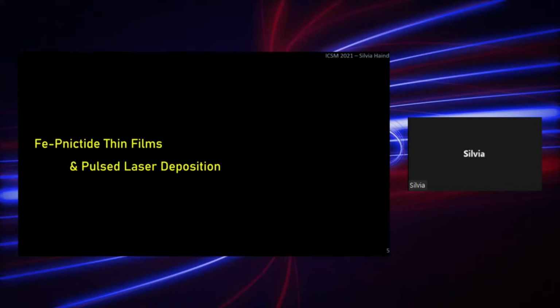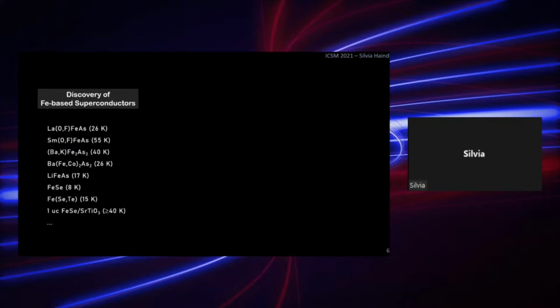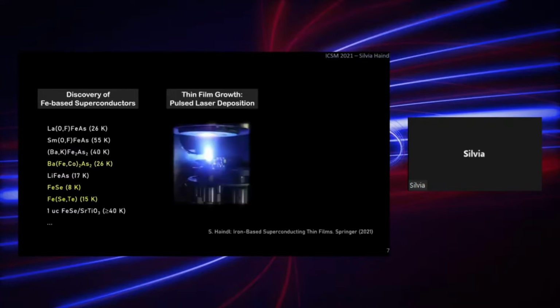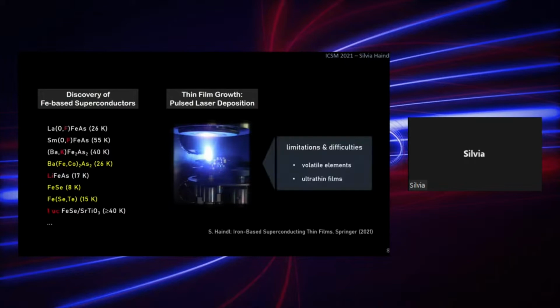So let me briefly introduce iron-pnictide thin films and pulsed laser deposition. Since 2008, we have faced the discovery of many iron-based superconducting compounds. However, if we deal with thin film growth and we choose a particular growth deposition method like pulsed laser deposition, we see that only a handful of compounds have been grown and studied successfully. And this has several reasons, and one of these reasons is that the method itself faces limitations and difficulties, for example, in the presence of volatile elements or when we want to grow ultra-thin films.